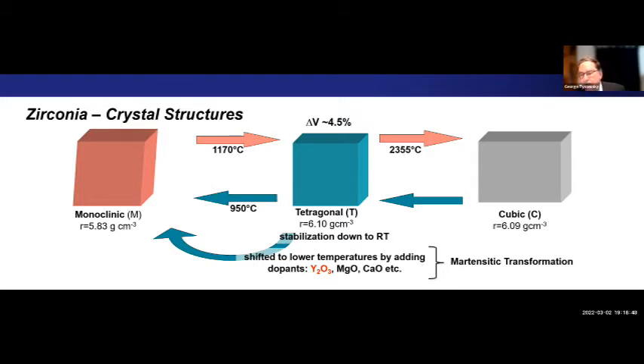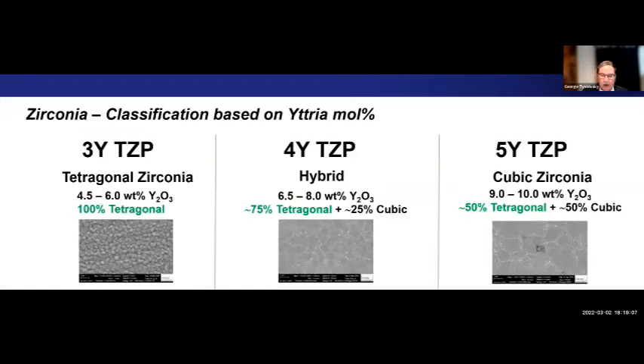What's happened over time as we looked for more translucency in the zirconia material is that we started adding cubic zirconia to the tetragonal phase. The issue is that the more cubic material we add, the higher the translucency, but it weakens the crystal structure of the zirconia material. So today in the marketplace, with the evolution of time, we started with the most stable material, which is 100% tetragonal. It's called 3Y zirconia, which is basically, with the amount of yttria established in the material, the strongest, most durable zirconia.